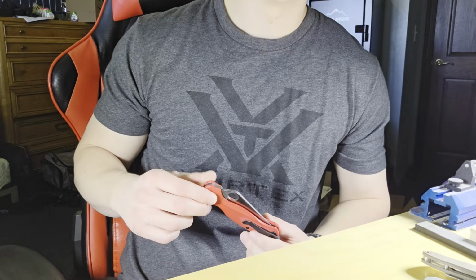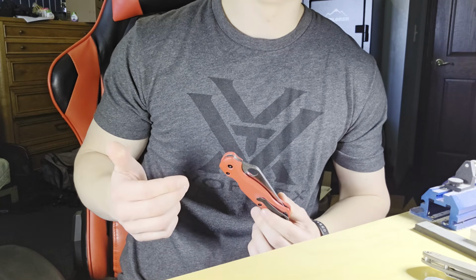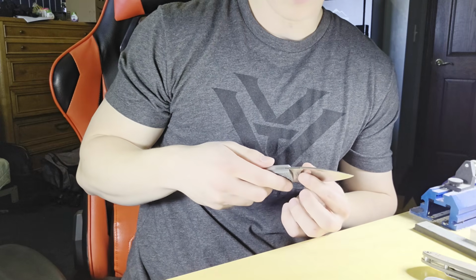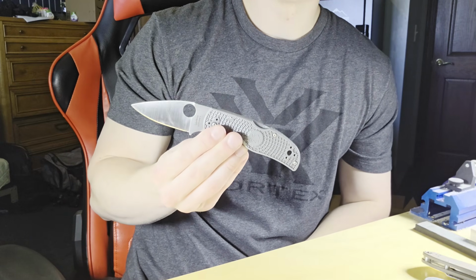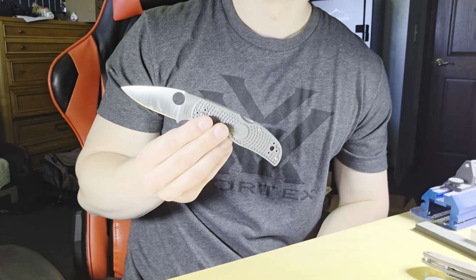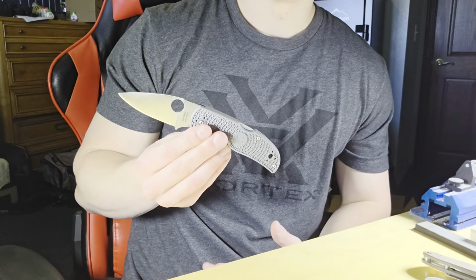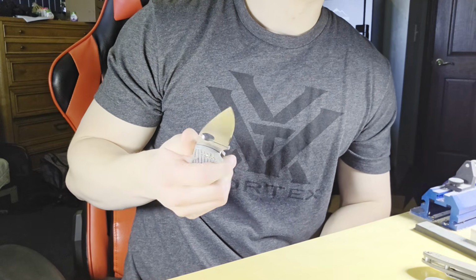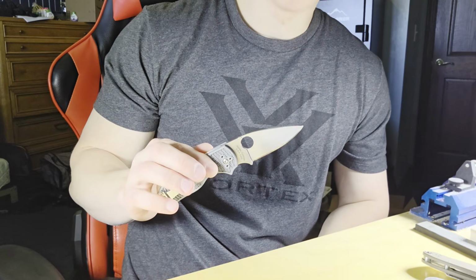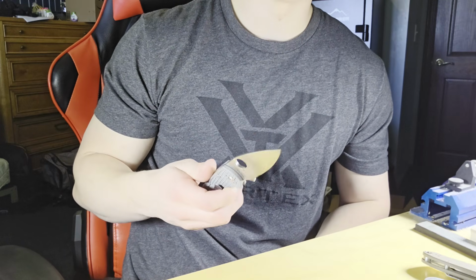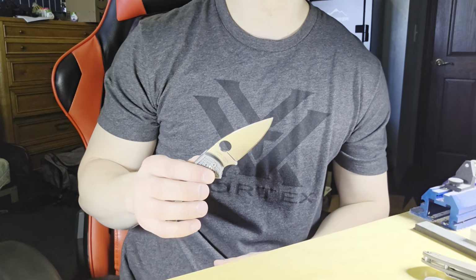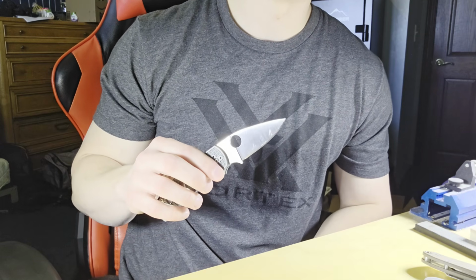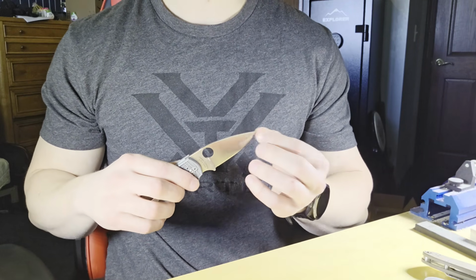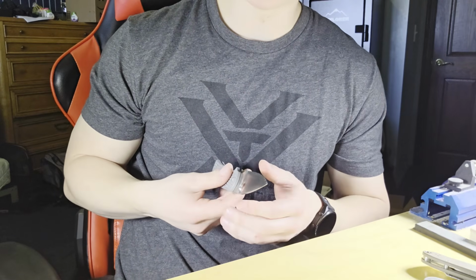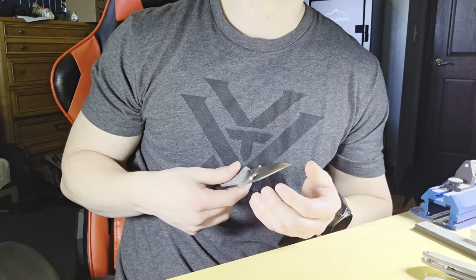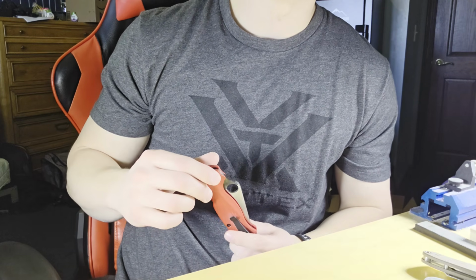We all know that higher hardness leads to lower toughness, which is your resistance to lateral stress, which is why you see Maxamet, if you're part of Facebook groups and stuff, you see these broken on a semi-regular basis because people use them for stuff that they're just not supposed to and they break. This is a very high hardness steel, high carbide steel, and it just doesn't do well with those stresses. With that being said, higher hardness does lead to an increase in edge strength, which is your resistance to edge deformation. So the mode of dulling is just going to be the flattening of the apex instead of any chipping or rolling.